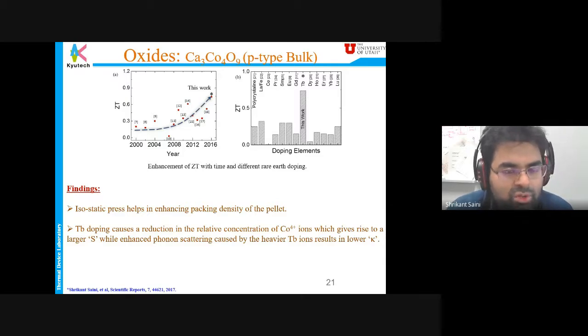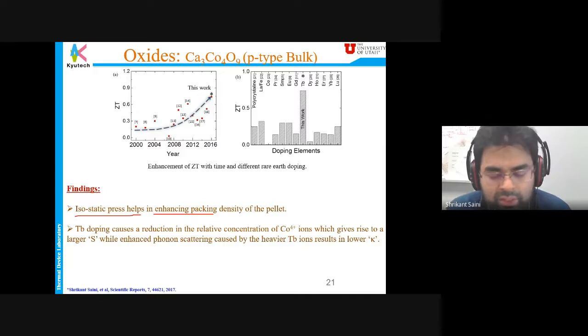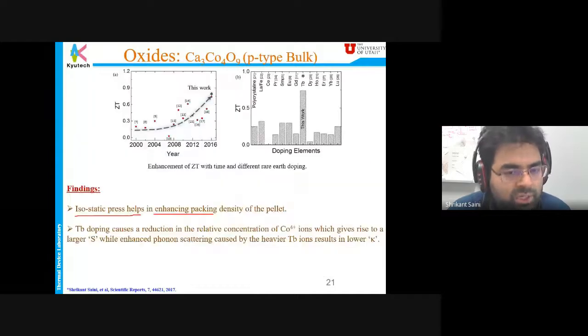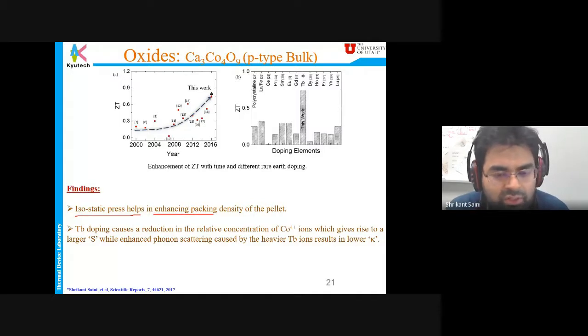What we understand during this project is that the isostatic press helps in enhancing the packing density of the pellet. That means the grains come closer together, they melt into each other, and they perform better electrical conductivity in this region, from one grain to the other grain. That's what we understand here. And the doping of terbium, or Tb, causes a reduction in the relative concentration of cobalt 4+ ion, which gives rise to the larger S while enhancing the phonon scattering.